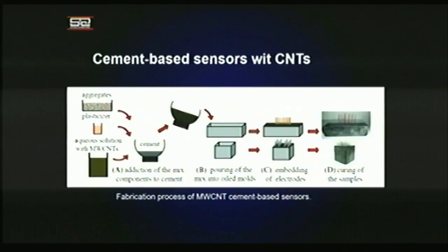It's quite simple. It is based on additives, that is, nanomaterial additives, carbon nanotubes, in particular multi-walled carbon nanotubes, being utilized here. That can be mixed with the concrete itself, and then you pour it into the molds, and you can insert the electrodes in order to measure the resistivity.